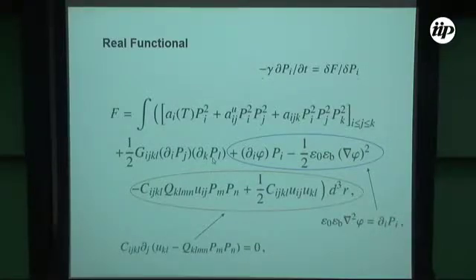Yeah. And now, this is the electrostatic part, which gives exactly this type of non-locality that is very, very difficult to treat. And another part is the elastic type coupling, which is quadratic over polarization and linear over the strain tensor. So C is the elastic stiffness tensor, and Q is the electrostrictive coefficients. Also it is assumed that they are taken from experiment, but it's not always available.